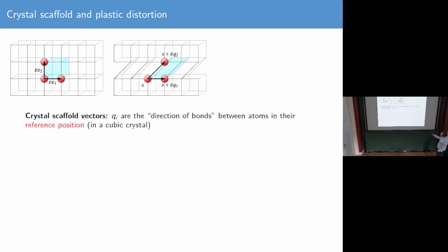Okay, so the idea is, this is my undistorted lattice and this is a distorted lattice, but what I've done here is I've actually kept the atoms in their place. I haven't moved them, they're pinned. What I have changed is the bond. My plastic deformation has moved this bond: it cut it and reconnected it to this one. I haven't yet acted on the fact that, by some elastic relaxation, this will of course mean that the top bit will shift to the left. I haven't done that yet.